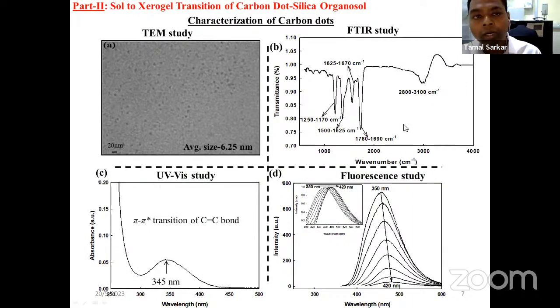Now I come to the part two study where I will incorporate the carbon dots inside this silica sol matrix. But first I have to synthesize and characterize the carbon dots. So these carbon dots were synthesized in the lab using a microwave pyrolysis method, and the TEM study shows that these gray spots are actually carbon dots, and they are closely spherical and uniformly dispersed, and the average size I got is 6.25 nanometer.